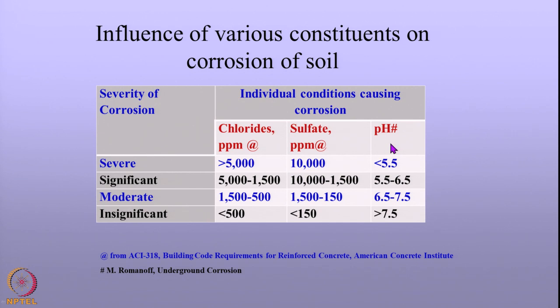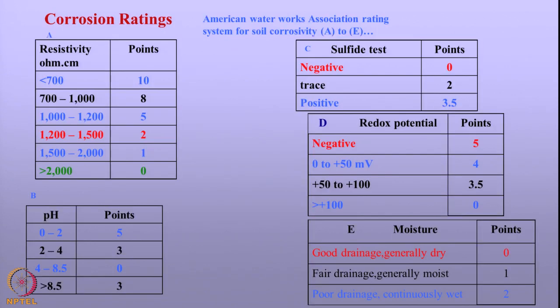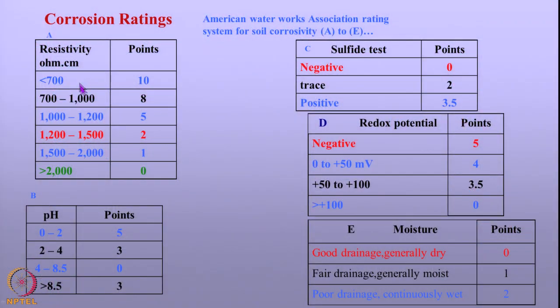So is the case with the pH. Lower pH means it is very severe, and at relatively neutral and alkaline pH, the corrosion becomes very insignificant. So, the soil chemistry is an important factor in the life of buried structures. In fact, the American Water Works Association has used some kind of rating to quantify soil corrosivity. They involve resistivity of the soil, the pH of the soil, the sulfide content of the soil, the redox potential of the soil, and the moisture content of the soil.